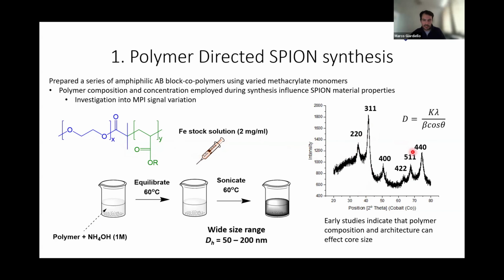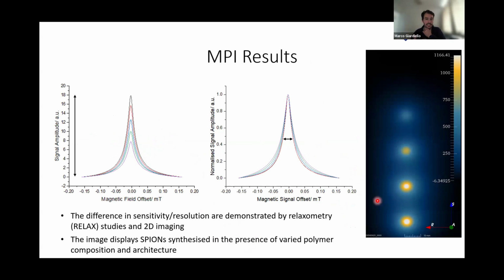I've just drawn an indicative XRD of these things, but we are seeing that, first of all, we are able to change the hydrodynamic diameter by varying the composition of the particles, and it is having an impact on the core size inside your sample, which is therefore, on the next slide, having an impact on the MPI data that we're seeing. Each of these contains the same amount of iron. These are various different samples, different compositions, different polymers, different concentrations of polymer relative to synthesis. It's showing that in our libraries we're able to tune how good they are as MPI agents by varying the composition. So we're showing structural change from the polymer perspective and how this affects your MPI signal.